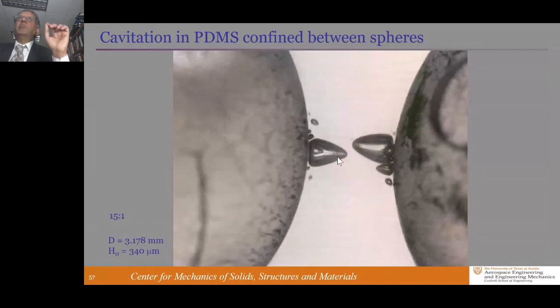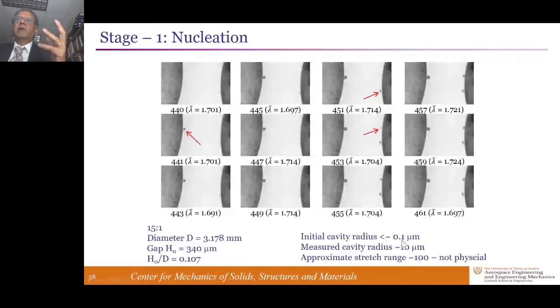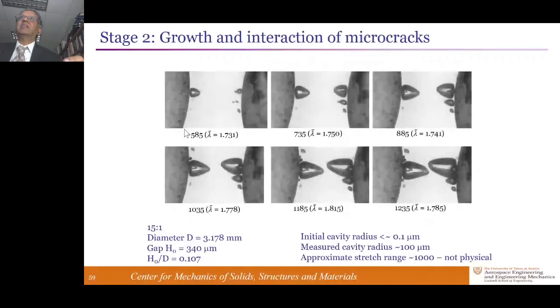So a very simple estimate of the size of the cavity when they first pop is it's about 10 microns. Initially, the defects are no larger than about 1/10 of a micron, because if they are larger than that, they'd be visible optically, but they're not seen in these images. So we assume that the largest possible flaw there is on the order of 0.1 micron, which means there is a factor of 100 between them. So the approximate guess for a stretch is about 100. This is physically unrealistic. No material, no PDMS is going to stretch to a factor of 100. So even when we see the first object that's there, it's not a cavity, but it's a crack. So fracture is an essential part.